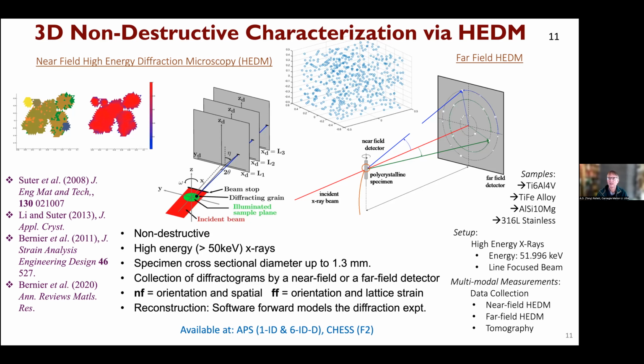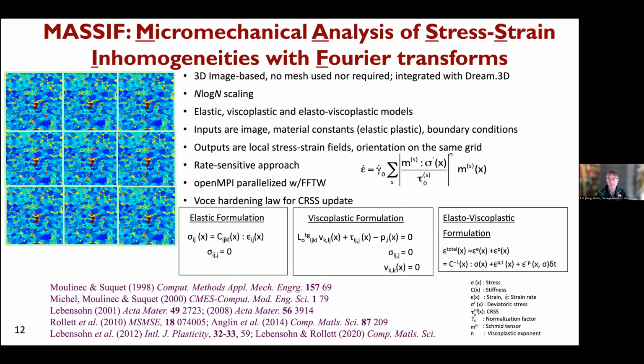Then to complement that, you need some way to calculate, at least we do in the kinds of problems we look at, full field micromechanical simulations. In other words, take the measured structure as the input and calculate for a given loading, what is the pattern of elastic strain and elastic stress, plus plastic deformation where appropriate. And most people would use finite element. We use a code that we like to refer to as MASSIF, micromechanical analysis of stress strain inhomogeneities with Fourier transforms. That's a rather fancy title for a code that's basically a spectral method and exploits the Green's function approach, but putting it all into frequency space to speed it up. That's the point of using the FFTs.